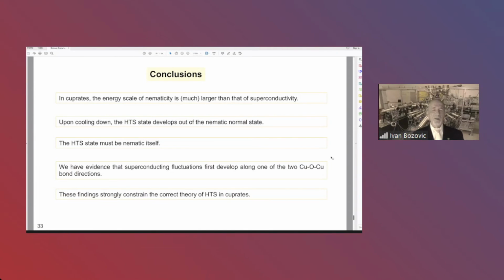And indeed, we have gathered some experimental evidence, not published so far, that the superconducting fluctuations first develop in one direction, along a copper-oxygen bond direction. And this is very hard to reconcile with the standard BCS theory, which postulates a Fermi liquid normal state. In any case, this very tightly constrains the correct theory of high-Tc in cuprates. It informs on the character of the pairing interaction, which appears to be anisotropic. Note that this is quite unexpected. If the crystal is C4 symmetric, then so must be its electron band structure, the spectra of phonons, magnons, other excitations, as well as their coupling. So this may prove to be a crucial issue.